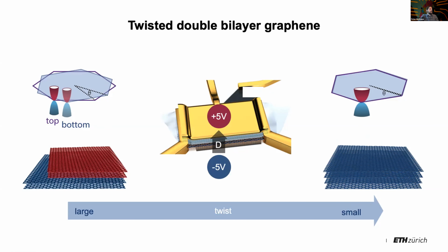And what this will do to the band structure, well, in this case here, you will see it shifts the cones up and down. So it just puts the top and the bottom layer on different energies. And additionally, it opens a band gap here. And this gap opening just comes from the fact that I have bilayer graphene, where a gap opens under the application of an external field. And in the tetralayer case, or if everything is coupled essentially, then I will just open a general gap.